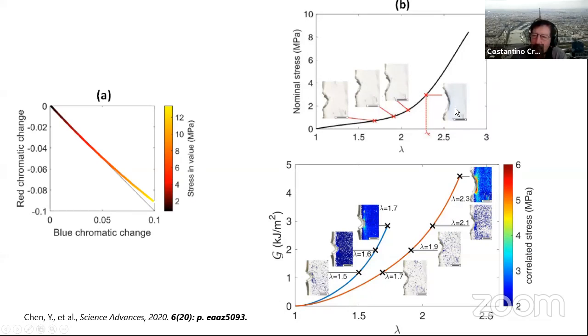If you look up on the upper image and you look close to the crack, which is at that point completely open, you should see a slight blue. I hope you can see it. Now, this slight blue in the raw data can be analyzed if you take the images and you properly normalize them and calibrate it, and you can extract from that a value that corresponds to the stress in uniaxial extension.